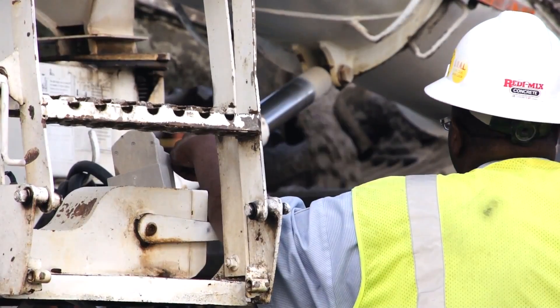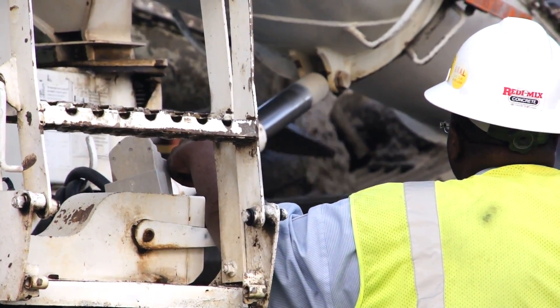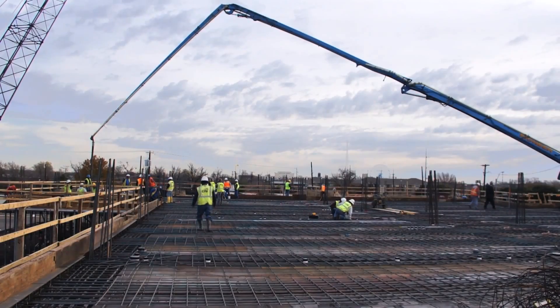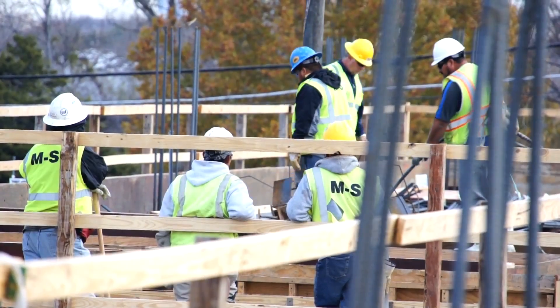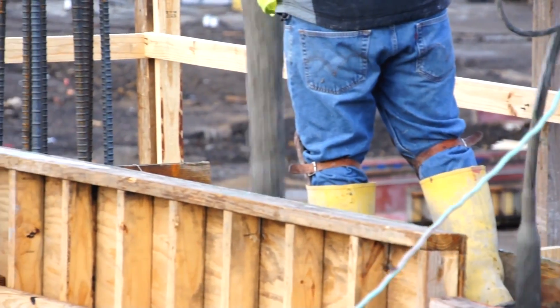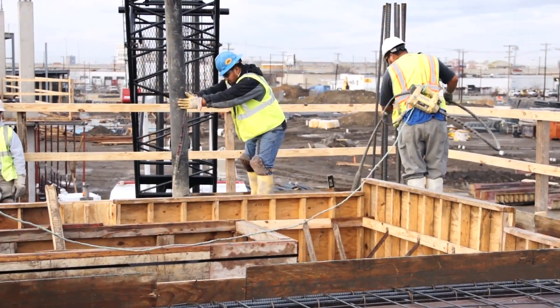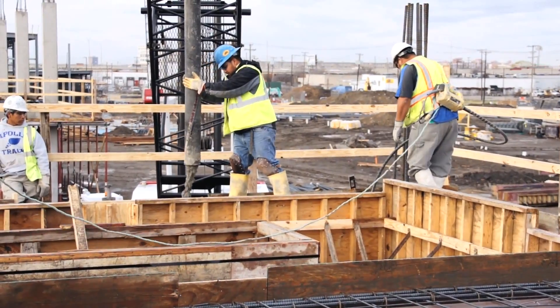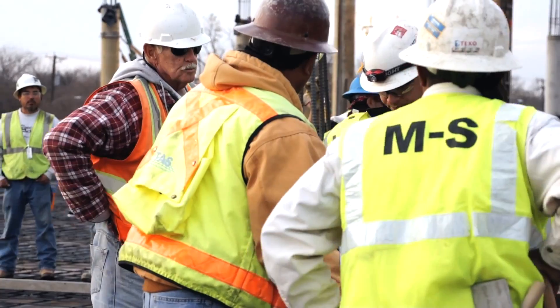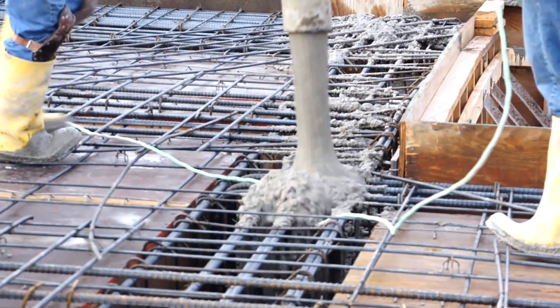The first challenge, obviously, is getting the structure in place. We're reaching full strengths within 48-72 hours, which is allowing us to strip formwork, remove shoring, put in the reshores, and provide the mechanical, electrical, and plumbing in the overhead spaces on the floor below. This allows us to break our times in the scheduled periods for the durations by two-thirds of the durations given.